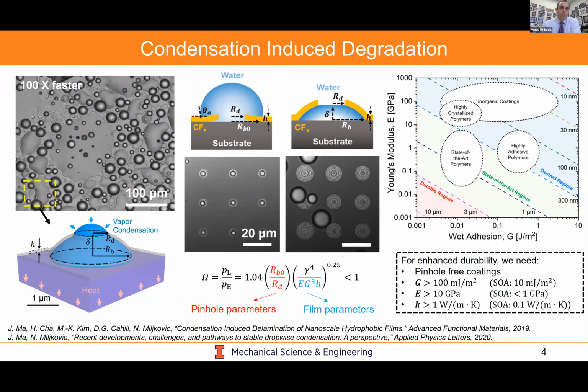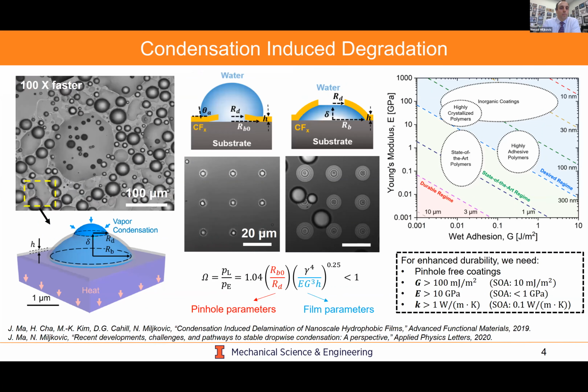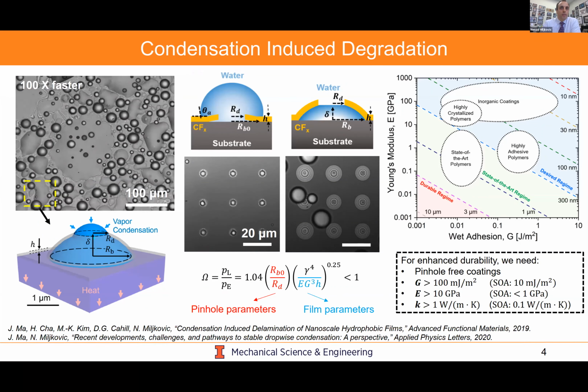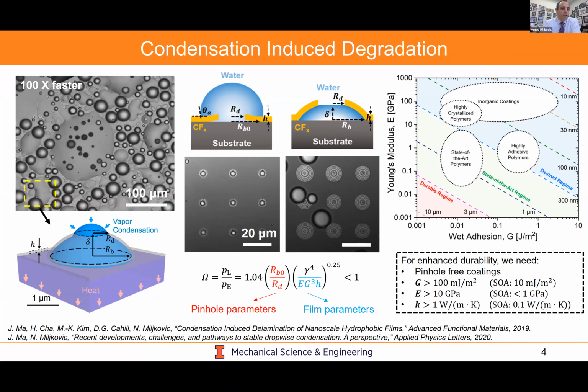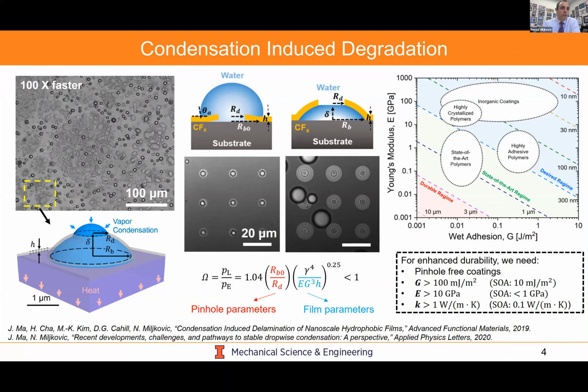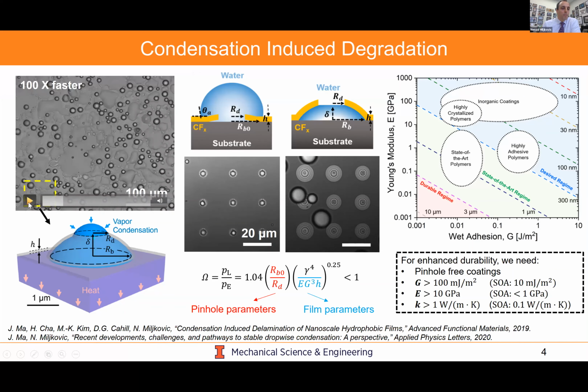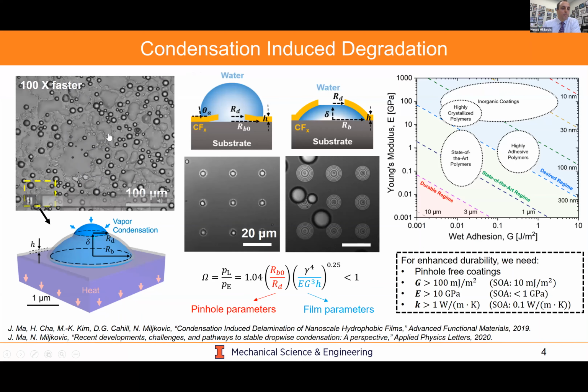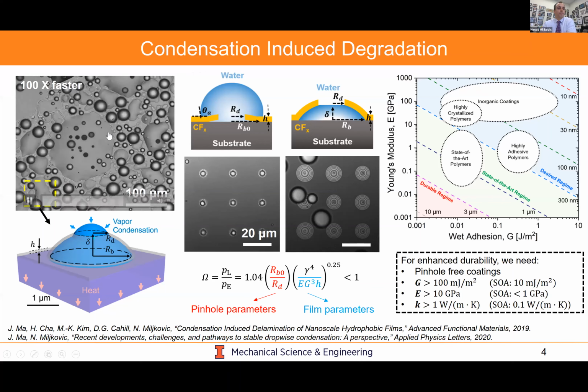So one of the most well-known and studied nano-engineered surface durability challenges, and Dan touched on this in his motivation in the beginning, is in dropwise condensation. Dropwise condensation is a century-old process, which is currently not used in any application really, mainly due to durability issues of the thin promoter film, which has to be placed on the metallic surface. So if you observe dropwise condensation using optical microscopy, what you'll see forming are these water blisters, which could actually take your nanoscale film, remove it from the surface, and delaminate it.